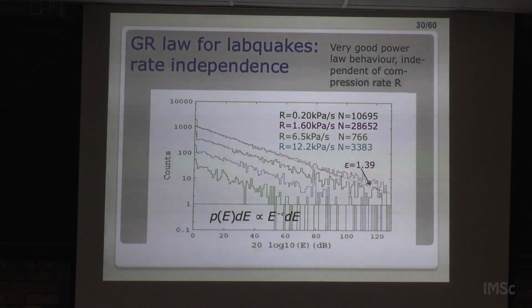But this exponent is different from 1.67. Yes, this is important. The exponent is around 1.4, 1.35, 1.36. It depends also. It's slightly different in the two mechanisms: the load control and the speed control. You will see. But it's not 1.66 in this case of systems. You will see, because these are the brittle ones.